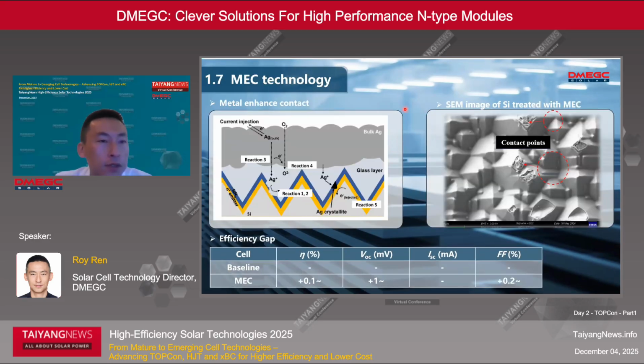Next is MEC technology. MEC means metal enhanced contact. Through the injection of current, a thermal effect is formed, which induces the connection of silver silicon alloy. Moreover, this will significantly reduce the damage to the passivation layer, thereby bringing about improvement in VOC and fill factor. In the SEM on the right, we can see the connection point at the top of the pyramid.